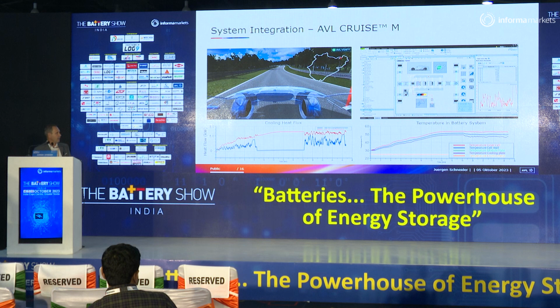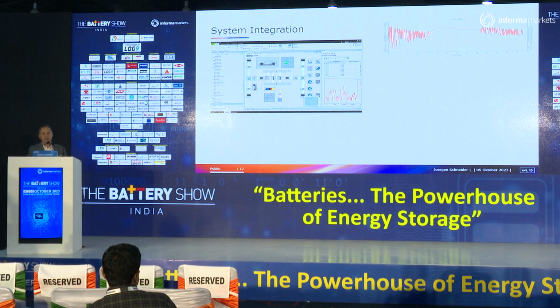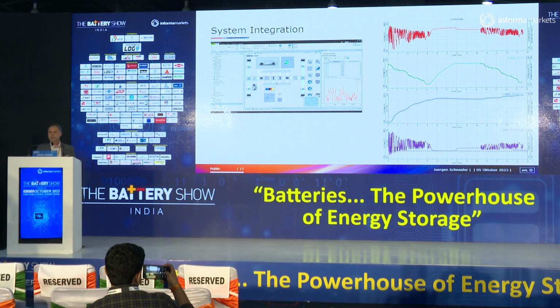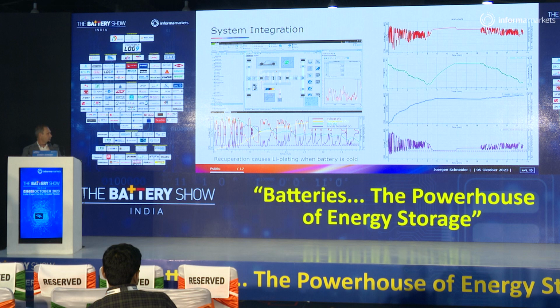We were also interested in what happens if I start at a low temperature, minus 10 degrees, and do hard cornering and hard braking, so recuperation. We can see here that when the temperature is cold, we have lithium plating and damage of the battery. If that happens for just a few seconds, that would not be a problem, but if you're permanently running under these conditions, this might cause accelerated aging of your battery.